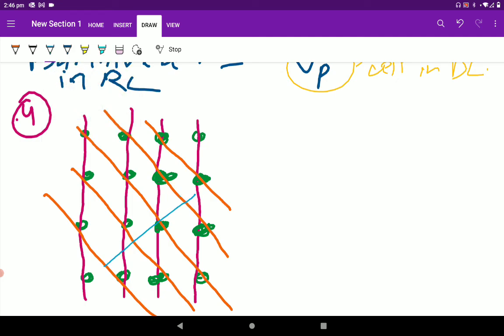This is perpendicular to this plane, so this vector is G of hkl, where the Miller indices are the same as obtained by intersecting the axes. So there always exists G hkl perpendicular to the planes, which means if you have a direct lattice and look at a family of planes, these indices are exactly obtained by this method.